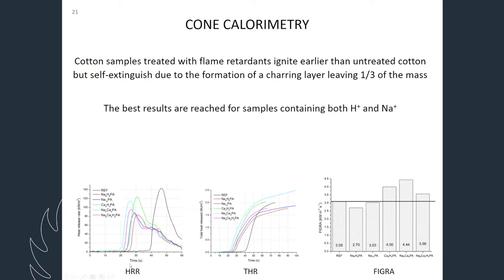One interesting thing you can see, we have shown three graphs. The first one is called HRR, that is heat release rate over time. So after 20 seconds, the treated samples, you can see, they started releasing heat, they start getting oxidized. But the untreated one actually resisted fire for a longer period. The treated pieces ignite earlier, but the interesting thing is that the treated ones actually retain much more mass after the burning.